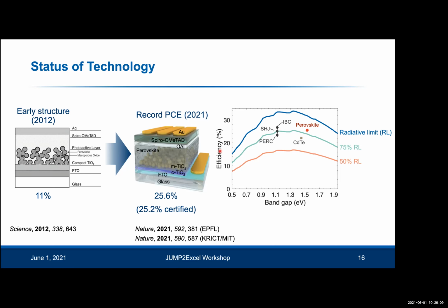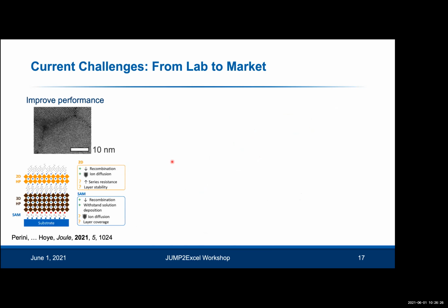And some of the recent advances which have led to these best efficiencies have included passivating the top surface, as well as passivating bulk defects within the perovskites, which is exactly what has been done with silicon to get the best efficiencies. So earlier this year, I and some other colleagues wrote a future energy piece for Joule to